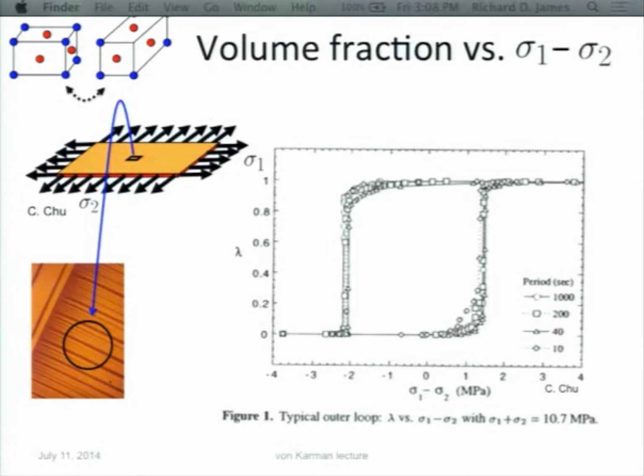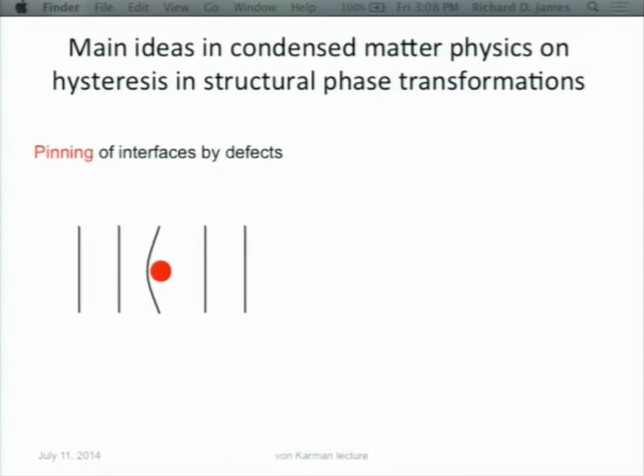Each dot corresponds to one of those measurements. In fact, it turned out it didn't matter where on the specimen you took that measurement, which is a very important observation, but I won't go into that. But anyway, the point is these are the rates of loading. It was a periodic loading program, and this period was 10 seconds, and this was 1,000 seconds. You can see that the size of the hysteresis loop is very nearly independent of the rate of loading. That's so-called rate-independent hysteresis, and it's the typical hysteresis in these materials, also for thermal hysteresis. Okay,